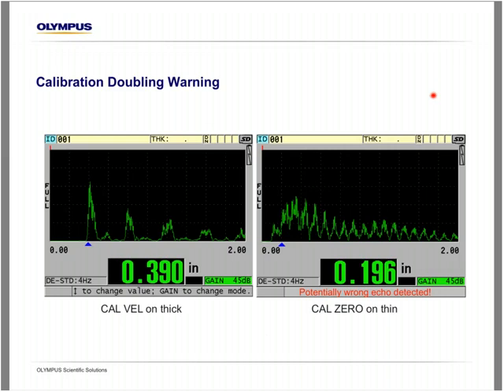So we actually build in a warning because of this. We have what we call the calibration doubling warning. So when you do your cal-vel on your thick, the instrument already kind of knows what the time of flight value should be based on what it determined in the cal velocity. So what it does is compare the time of flight from the thin test block, cal 0, to the expected time based on that cal-vel.